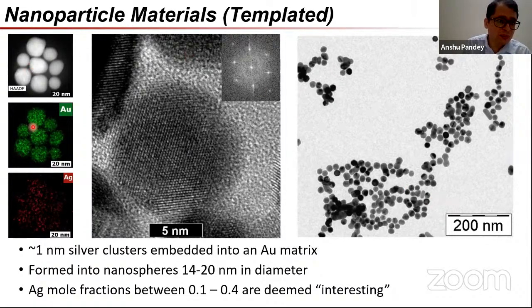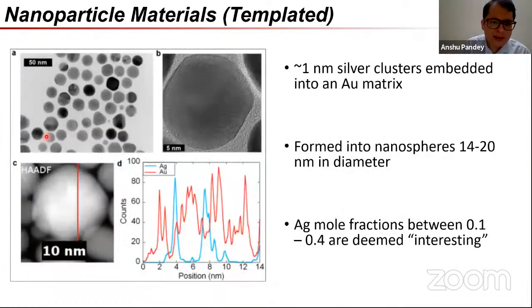As you can see, based on these elemental contrast mappings, you see around 1 nanometer silver clusters embedded into a gold matrix. This is not, of course, very good for telling you the size of the particles. I'll show you the sizing information collected via AFM towards the end. But generally, these are a random dispersion of silver embedded into gold, as shown in these figures. This is again just a mapping of how silver and gold are distributed along this red line, and you find that there are discrete occurrences of silver against a near-continuum background of gold. So, these materials we were able to see to a reasonable extent.